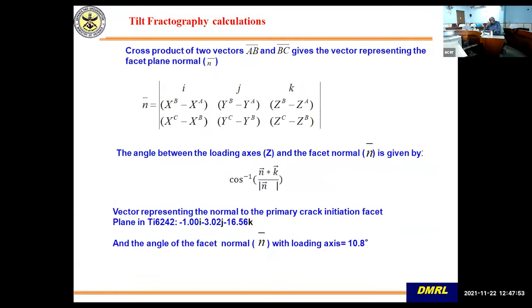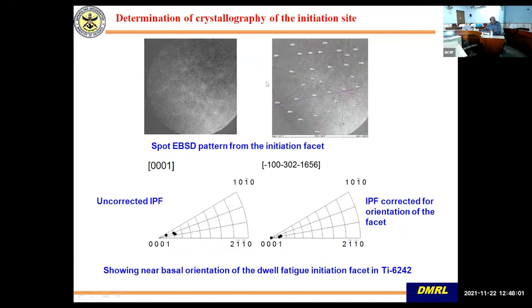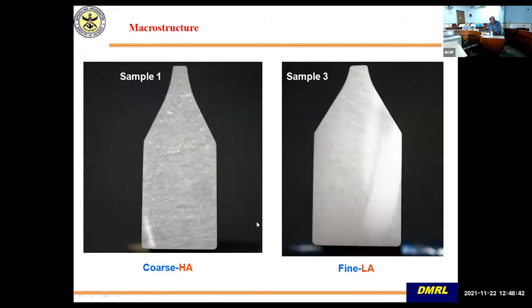So you can calculate both the physical orientation and also the crystallographic orientation of the facet by pulling out a pattern from the faceted region, and then if you plot, it is the near basal region as Bache had predicted. So these are the crack initiation regions. Okay, so the hard orientation regions are the regions which start cracking. So that is what this study shows, as is shown also on the EBSD around the secondary crack. Even if you analyze the primary crack also, the crack initiation region is around the hard orientation. Okay. Now, then we were given pieces of rings which were processed differently.